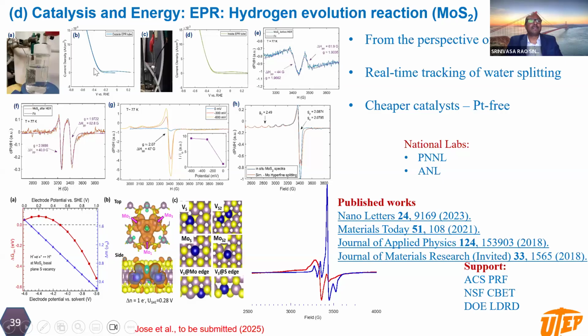And we mimic the same experiment by shrinking this big size beaker into a millimeter size beaker here. So we put all the electrodes inside a millimeter size beaker, and we use molybdenum sulfide catalyst, and we produce hydrogen gas, and we tracked its current versus voltage behavior, and that number is matching with the reported number. And going further, you see electron spin resonance signals before and after the reaction. Okay, so you see two distinct EPR signals, and that is well known, as people already reported what happens to this compound before electrocatalysis takes place. What is unknown is what happens to the signals during the reaction.